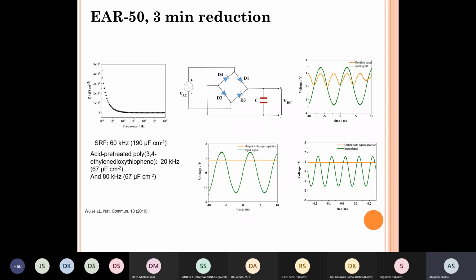Okay, so this is a glimpse of the fact that pseudocapacitors, which were generally considered to be always low performing compared to EDLCs in terms of speed, it is possible to engineer them, both by nanostructuring, by having nanoparticles clustered around a straight lumen, and also some defect engineering to introduce oxygen vacancies and thereby increase the conductivity to still get a fast response pseudocapacitor. Once you get a pseudocapacitor, then the capacitance is always going to be higher than EDLC electrodes.